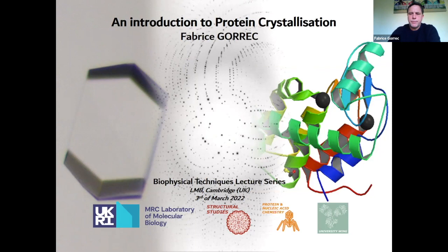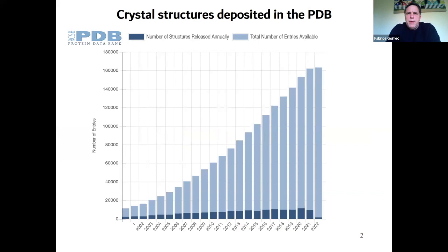So here you see the crystal structures deposited in the PDB since 2000. You can see that according to the total number of entries in light blue, we are now above 160,000 structures. And there's a steady pace for a decade now of 10,000 structures released annually. And this is crystal structures by X-ray crystallography, so it doesn't take into consideration a small proportion of interesting structures solved by neutron diffraction. There's an increasing number of structures solved with X-ray lasers.